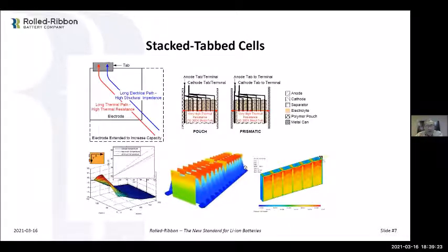And so you see that. And again, these are models from NREL. So if you look at the electrode shape here, what happens is you'll see all of the heat will elevate here as it exits where the tab's at, and you get this uneven heating on the surface of that sheet. And then as you make them bigger, the problem just gets worse and worse.